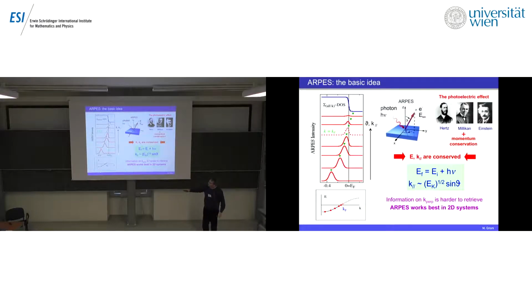So this is an idealized experiment. You have, say, a metal with a band crossing the Fermi energy at some Fermi wave vector. Now we emit photoelectrons and measure the photoelectrons at different emission angles, which correspond to different momenta. And what we see then is some spectral feature dispersing in energy, reproducing the dispersion of the band until it hits the chemical potential and it disappears, of course. If we care to sum all these results, so sum over all the momenta, then we should be able to recover the density of states, the momentum-integrated density of states.